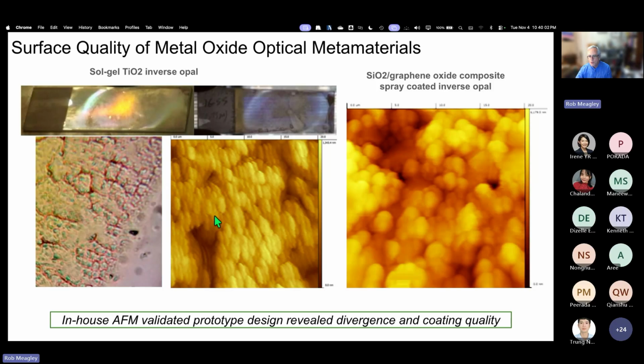In the nGauge, it was trivial. We can see that they're slightly elongated spheres. The cracks are clustering behavior among the spheres, and we can then start to understand a lot more about how the surface relates to the optical properties that we saw, including, for instance, how the yellow fades to red as you change your angle of incidence, and the fact that we did have significant defectivity. In fact, the material worked quite well for our purpose, and we were able to use a very low-cost coating method to get this performance.